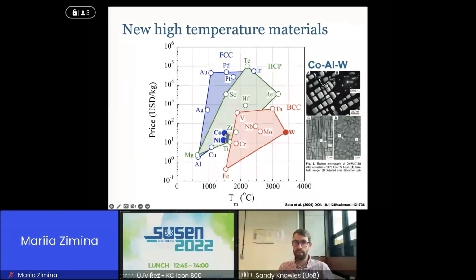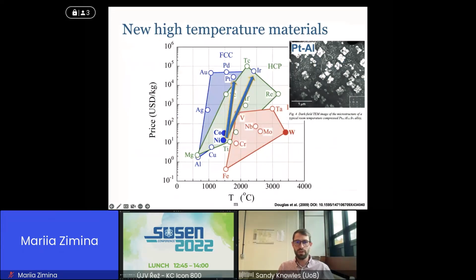If you shift from nickel to cobalt, you can get very similar microstructures, this gamma prime microstructure, and you potentially get some gains. There's lots of work, and I believe some commercial alloys now in these cobalt systems. You could then go a little bit more exotic if you choose other FCC metals, like a platinum-based superalloy, or an iridium superalloy, and you could probably build a jet engine out of them, but you might need quite deep pockets to buy your platinum, and probably armed guards around your airfields to stop people breaking in to steal it. I think also you come up against availability. There's just physically not enough platinum to build jet engines out of platinum. But there are some application areas where you could consider them if they're high performance but small volume.